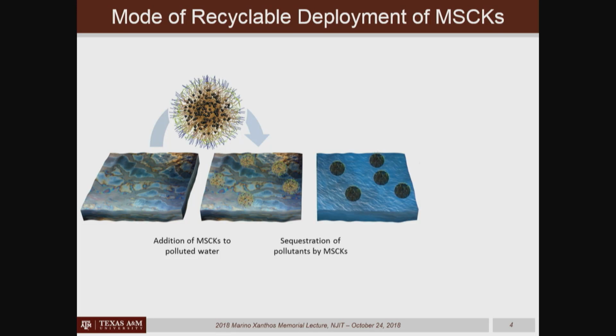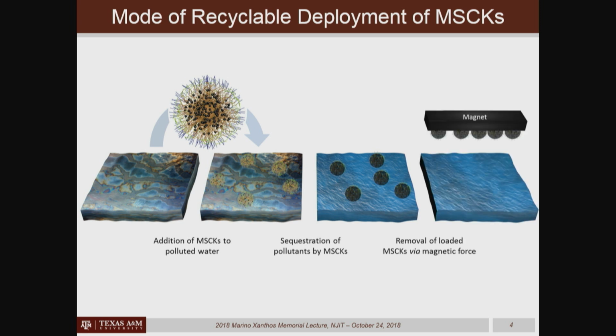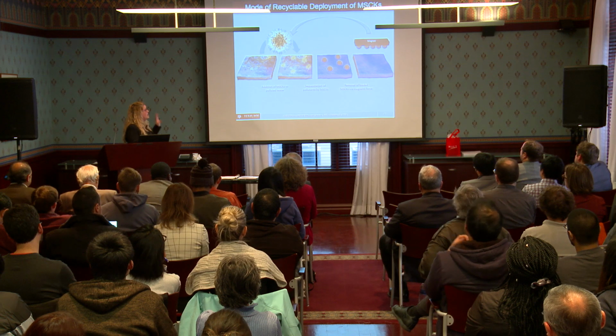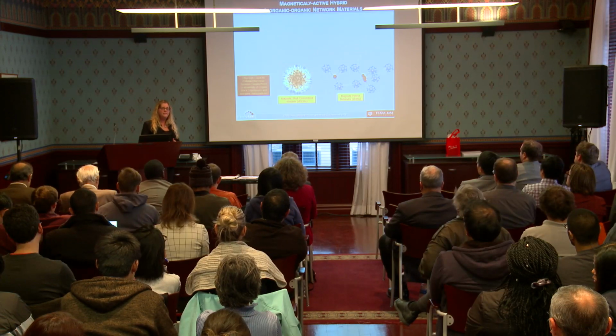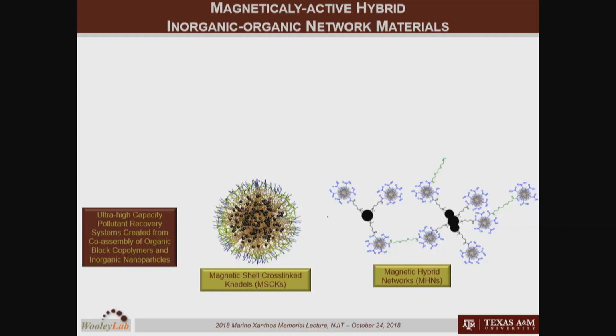And instead, if we could put out those dispersants in such a way as they could capture the crude oil by sequestration, as dispersants would do by their hydrophobic core interacting with the hydrophobic hydrocarbons of the crude oil, then by having magnetic responsivity, a magnet could be used to retrieve those materials, collect them, and if the oil could be extracted, then they might be able to be recycled and reused. So that was the overall approach, and we designed two different kinds of hybrid materials to do this. One of them is illustrated, as I've shown previously, where there's a polymer framework into which are embedded inorganic magnetic nanoparticles. The other, instead, has inorganic magnetic nanoparticles as central foci onto which are coupled organic polymer particles